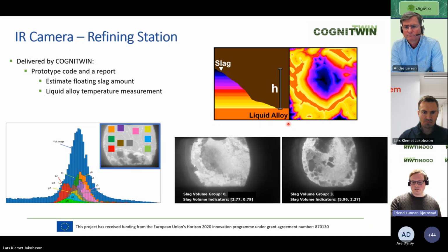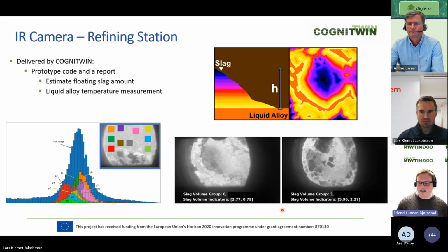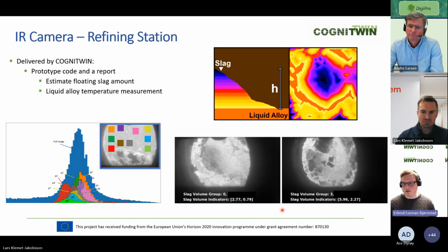For measuring, here you can see below there are two different images of slags. So here we have what we call volume slag indicators. The lower the number, the lower the slag. So here you can see two differences, and these fit very well with what we observe. And then we also have to try to estimate the temperature of the liquid alloy. One of the problems that we saw was that at different points in the alloy, we get different temperatures.